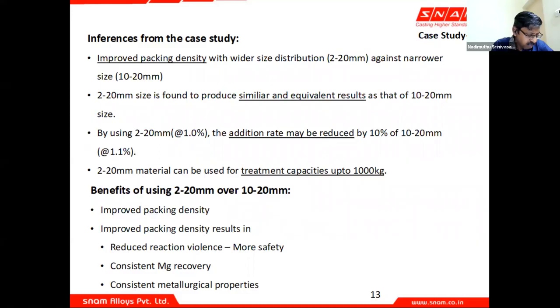So what are the inferences from the case study? You can find an improved packing density when you have a wider distribution. A 2 to 20 mm size is found to produce similar or equivalent results as of 10 to 20. Another thing we can find is, even with a 1% addition rate, compared to 10 to 20 of 1.1, you are able to get the result, which means there is a possibility of reduction in the usage of the alloy by changing the size distribution of the alloy.